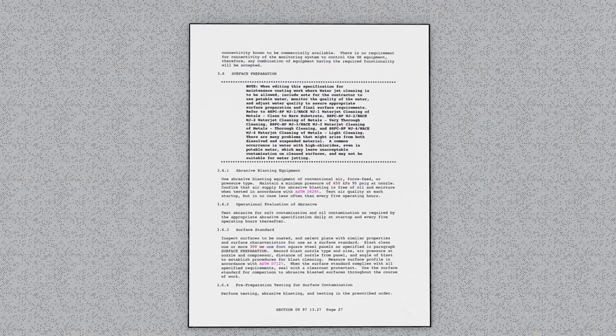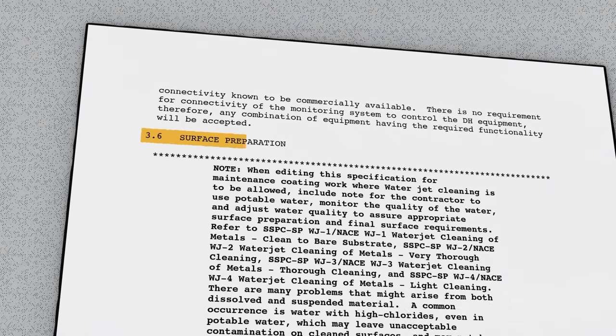If you take a peek into this specification, you'll see that a significant portion of the work isn't the coating application itself, but the preparation of the steel surface beforehand. It's estimated that surface prep makes up around 70% of the cost of a coating system, and that 80% of coating failures can be attributed to inadequate surface preparation.